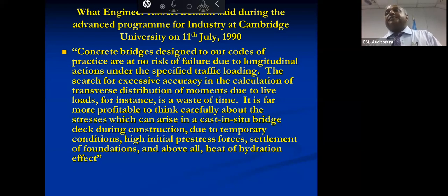Not much attention was paid in the bridges, bridge foundations, especially the pile caps. And the temperature went above 70 degrees, and we had severe cracking in those pile caps due to delayed ettringite formation. So heat of hydration is a very important topic, and in the lecture series, I have shown how that can be handled.